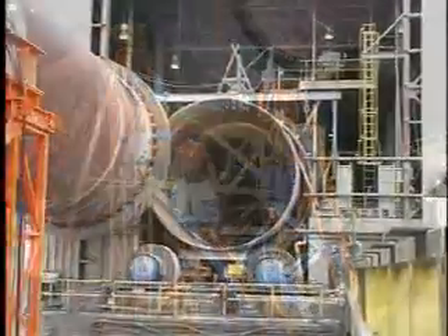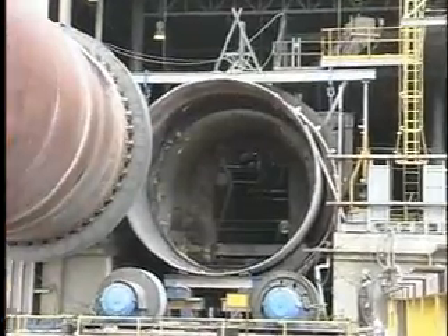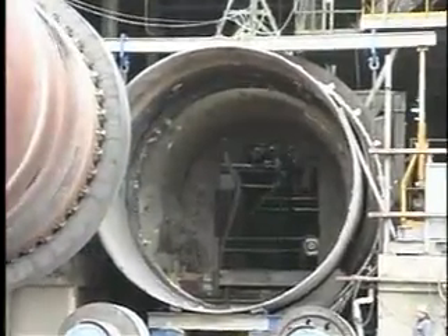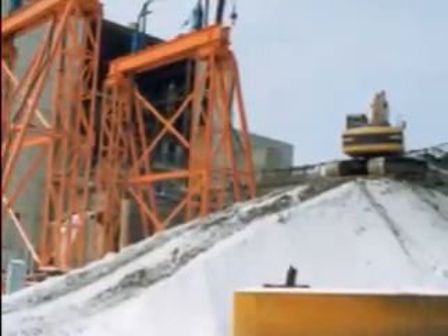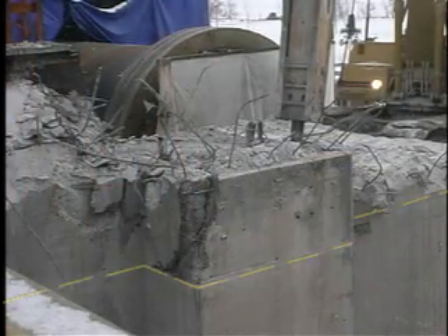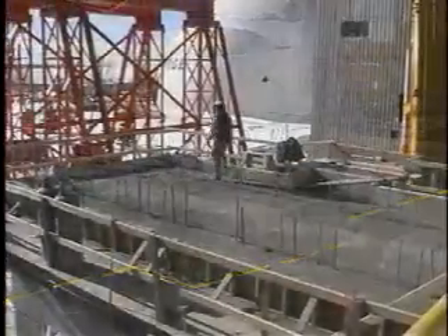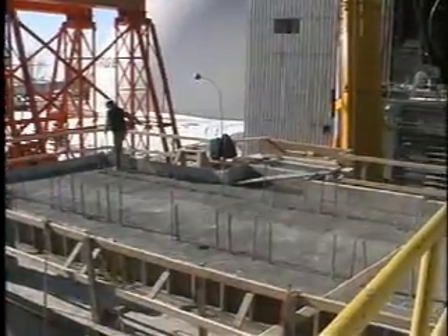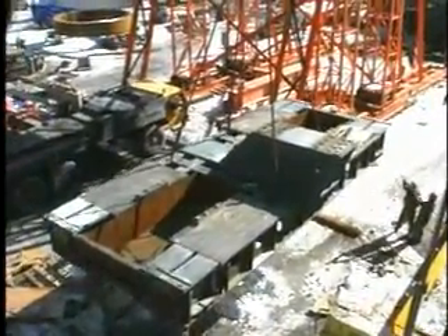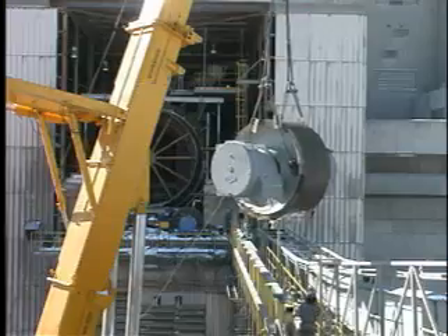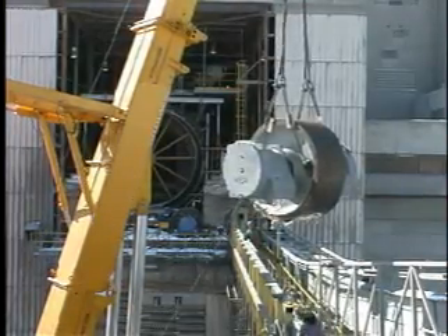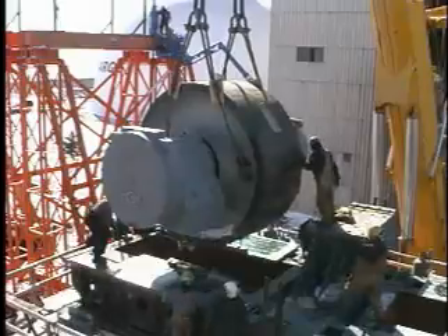The remaining outlet section inside the burner building and supported by the 40-ton gantry was then removed using a 250-ton Krupp mobile crane. Because the new spline tire was significantly larger than the old tire, concrete pier number 2 had to be cut down by approximately 4 feet and recapped for the geometry of the new roller station. Upon completion of the pier number 2 rebuild, the base frame and pre-assembled roller components, weighing 106 tons apiece, were hoisted using a 400-ton Liebherr mobile crane rigged with a superlift attachment and installed subject to critical alignment tolerances.